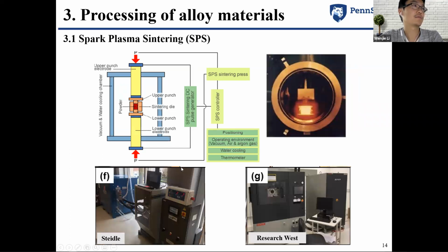And then for the processing of the alloy materials, in our lab, we basically use two methods. One is spark plasma sintering. Maybe most of you are familiar with this method. As compared to the conventional sintering method, for SPS, the current can go through both the materials themselves and the graphite dies surrounding the materials. In that case, we can provide a really high heating rate in order to maintain the intrinsic properties of the materials, like the nanostructures. And we basically have two SPS setups.